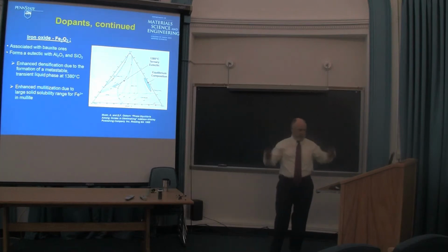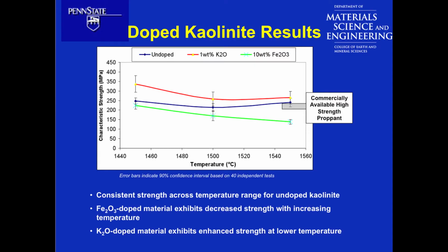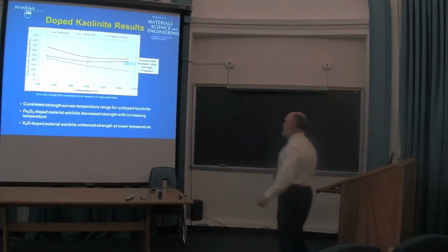So, two dopants, potassium, iron oxide. Then we go and we test particle strengths. We take individual particles after they're sintered and we squeeze them in an Instron machine and we measure the load to failure and hence the tensile stress, which will be right in the middle of the particles at which they break. And we relate that to American Petroleum Institute tests, tell us whether or not it should be a good proppant. Right? This is what we get.